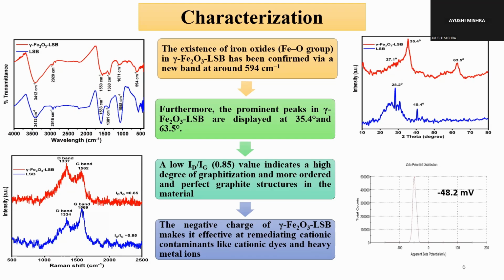In the Raman spectra, we have the D and G bands. The ID/IG ratio comes out to be similar, at 0.85. The zeta potential of the magnetic biochar comes out to be minus 48.2 millivolts. That shows the surface of the magnetic biochar is negatively charged. It would be a good adsorbent for cationic adsorbates like cationic metal ions or cationic dyes.